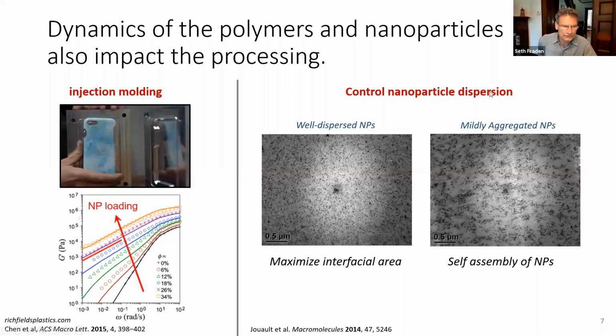Wait, I'm confused. So this says, is that G prime or G double prime? Oh, that's G prime. But you were talking about viscosity. Sorry, slip. Yeah, so viscosity will go up as well. But again, this is just to highlight the fact that as you add in particles, you're going to increase the resistance to flow, and that's going to have processing implications. And so it's like the more stiff, the higher the modulus, then the less it fills those intricate features? You want the low modulus for the intricate features?